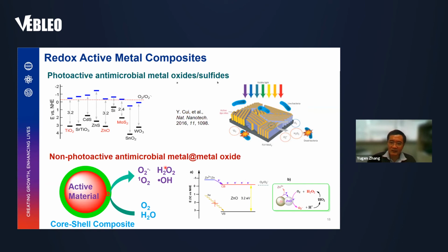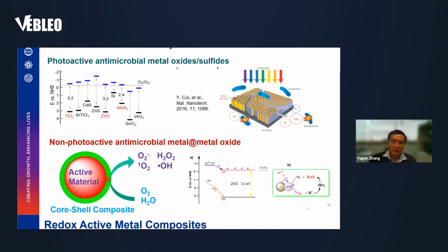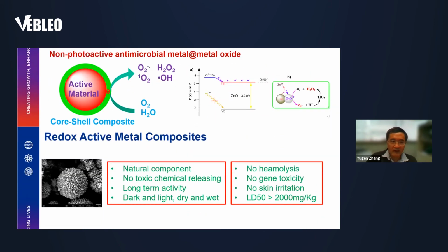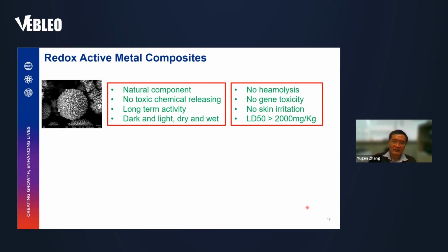And this conversion is basically by electron donation from zinc to zinc oxide, core and shell. And then they can reduce oxygen to superoxide and further convert to hydrogen peroxide or others. So with this design, the material is basically synthesized from natural components. They are non-toxic. They do not have toxic chemical release. They have long-term activity, and they can work in the dark. They do not need light and all those conditions.